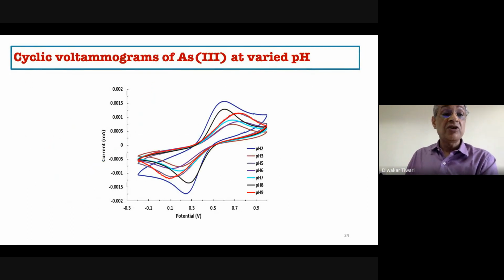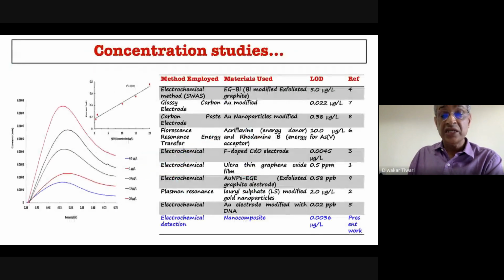The other aspect is the cyclic voltammogram of arsenic 3 that we obtained at different pH, and we found that lower pH is better in the detection system, because the current we observed for the oxidation or the reduction of this arsenic 3 was much enhanced at the lower pH.